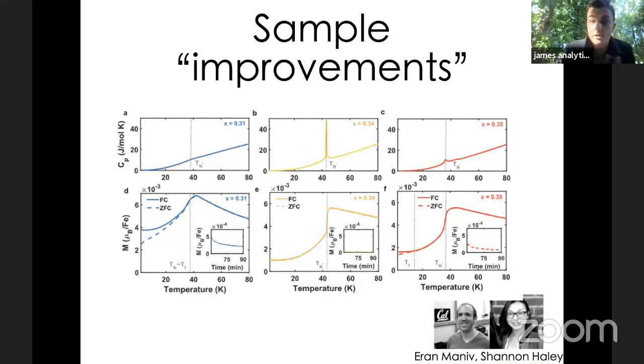But before I get to the more interesting stuff, let me just show you the basic measurements. So here's a system going from under 1/3 to around 1/3 to over 1/3. So going from the stoichiometric structure and disordering it in either direction. And I've shown you here in the top row heat capacity measurements across the magnetic transition, and in the bottom row magnetization. And you see exactly what you'd expect for the effective disorder on a magnetic system. When you add disorder, you strongly suppress the heat capacity anomaly. So near 1/3, it's a very, very sharp heat capacity anomaly and broadened either side. Similar effects in the magnetization. You see a very, very sharp transition near stoichiometry, but it broadens when you take away some of the iron and create vacancies, or when you add iron and create more interstitials. So disorder is bad for the antiferromagnetism, it seems. Okay.